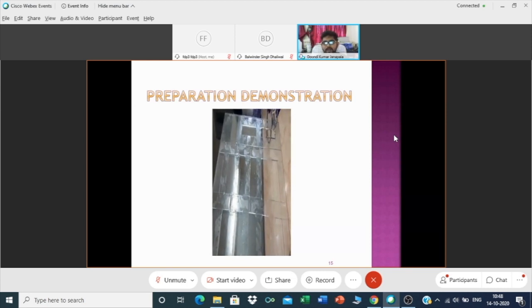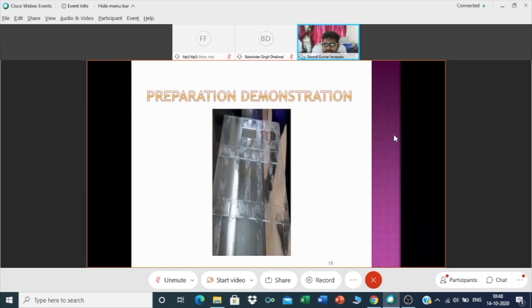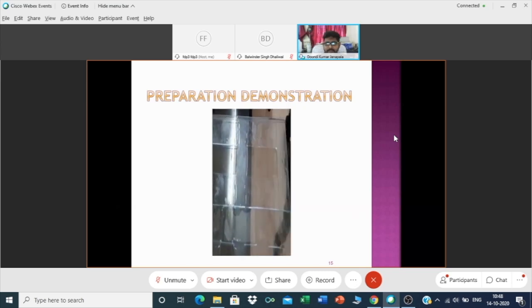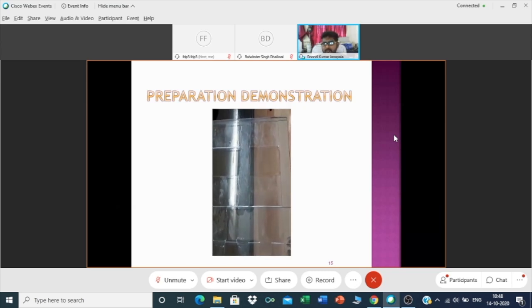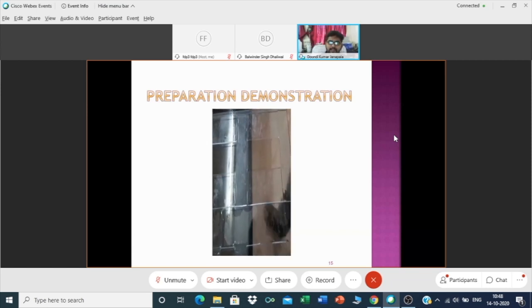Now, with this particular polymer, after pouring you should be very patient. You should have a lot of patience first, because if after pouring you directly put it in the baking, what happens is most of our constructions are such that one side will be a little slanted. So when you put it here, slowly the liquid will come to one side and get baked, and you can see that on one side the polymer is high and on the other side the polymer thickness is less. So you will get a polymer which is very uneven in thickness that you can't use. So that is why you need to put it outside for at least 2 to 3 hours,